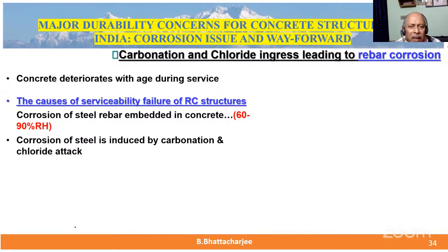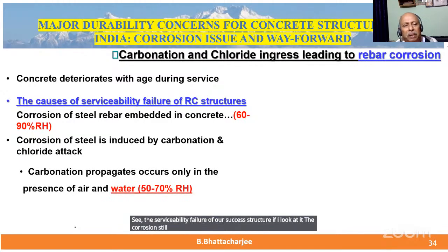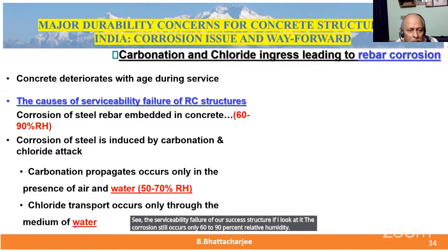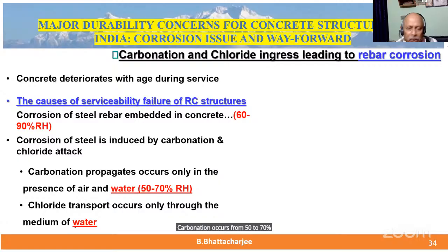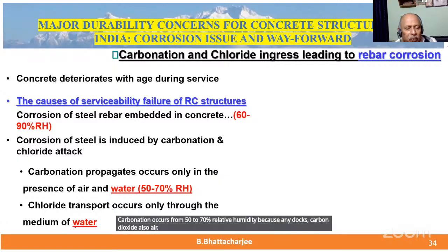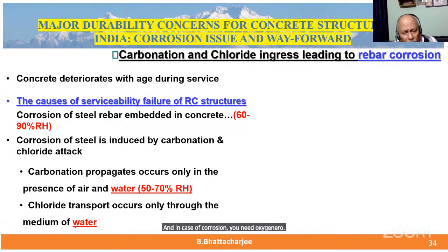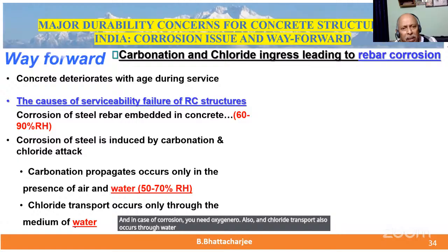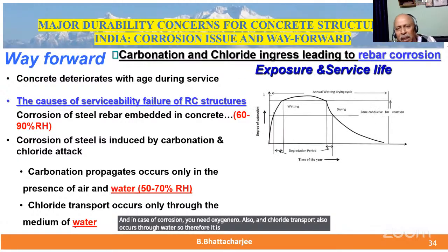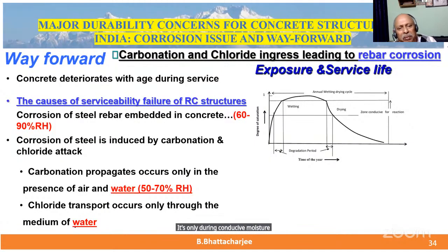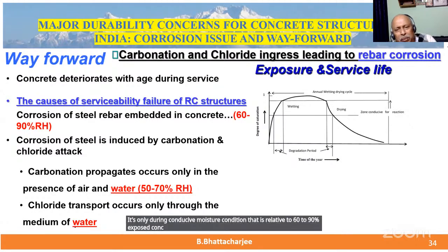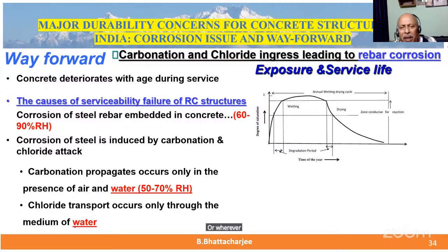See the serviceability failure of RCC structure. If I look at it, the corrosion of steel occurs only at 60 to 90% relative humidity. Carbonation occurs from 50 to 70% relative humidity, because you need carbon dioxide from air. And in the case of corrosion, you need oxygen also. And chloride transport also occurs through water. So if you expose concrete all the time, it is not susceptible to deterioration. It's only during conducive moisture conditions, that is relative humidity of 60 to 90%, in concrete exposed to air, that carbonation would occur, say at 50 to 70% relative humidity in the cover zone.